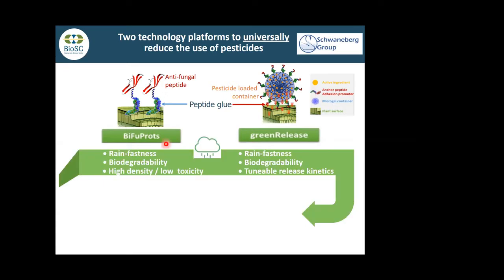You can tune the cross-linking density and the release kinetics over days or weeks. These adhesion-promoting peptides have a three-dimensional structure, usually in the size of 2 to 5 nanometers. They can glue very strongly onto surfaces — much stronger than standard polymer formulations. Since they are peptides, they are of course biodegradable. When you quantify them on the surface per square centimeter, you have more than a million of these adhesion-promoting peptides — it's really a very dense coating.